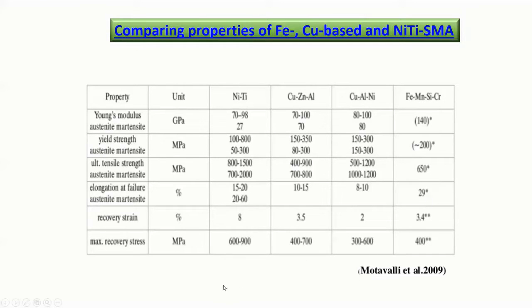And you can see that the Young's modulus, the strength, elongation, recoverability, strain are everything different for all of them. And if we look into this carefully, we will see that for the case of nickel titanium, these values are actually quite high. Coming to the strength part, you can see that these values are quite high compared to the copper based or even the iron based system. And the recovery strain, as I said, is of course much higher compared to any other kind of alloys. Okay, and what we are seeing low here is the Young's modulus, which actually we prefer to have low if we are thinking of the biomedical kind of application.